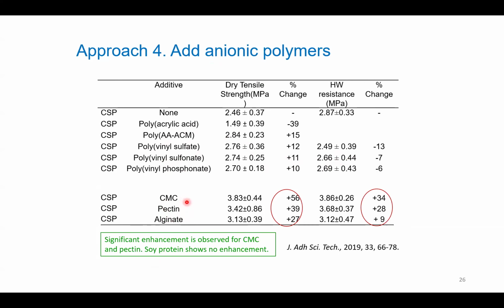The carboxymethyl cellulose increases the dry strength by 56% and the wet strength by 34%, a huge improvement. The low methoxy pectin also improves it fairly well, 39% and 28% respectively for dry and wet. And alginate somewhat less, but it also improves it. So basically, we see significant enhancement for CMC and pectin.